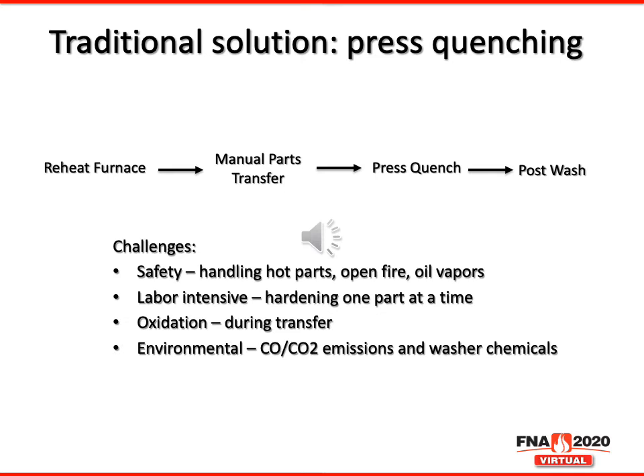Well, first the parts are put into a reheat furnace. Then they're manually transferred, usually by a person, an operator, to the press quench machine. In that press quench machine, the parts are set in a die that then encapsulates the entire part, and the part is immersed in oil for quenching. This die prevents distortion by simply holding the part in place. Once this is done, the part is removed from the quench machine and taken for a post-wash.